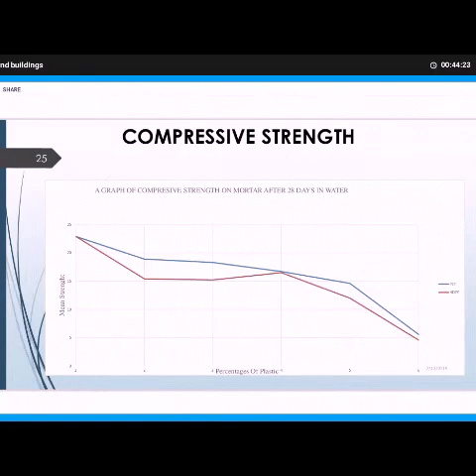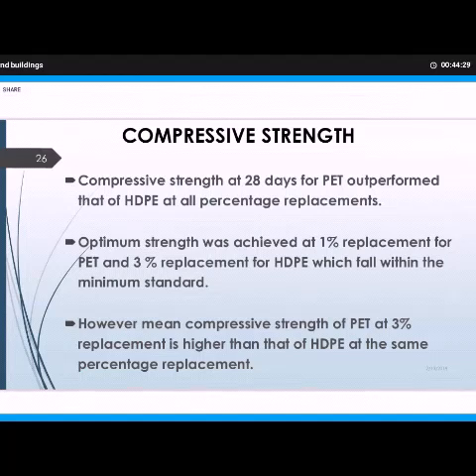Compressive strength. With the compressive strength as shown in the graph, the compressive strength at 28 days for PET and HDPE at all the percentage replacements, and the percentage replacements were from 1% to 5%. The optimum strength was achieved at 1% replacement for PET, that is the polyethylene terephthalate, and 3% for HDPE, that is the high density polyethylene, within the minimum standard. However, for the mean compressive strength of PET at 3% replacement, the strength was found to be higher than that of the HDPE at 3% replacement.